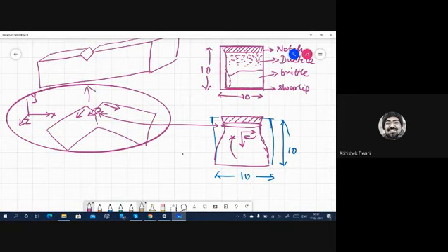So this dimension is much farther away and constrained from the crack tip or the notch tip, but the adjacent surfaces are closer to the crack front. So the material is being pulled, sinking in where they are getting pulled apart. Because of that, there will be a sinking, and to keep the volume constant in the flow, it will take this kind of shape.